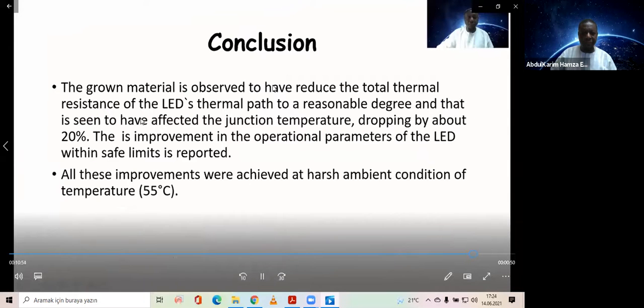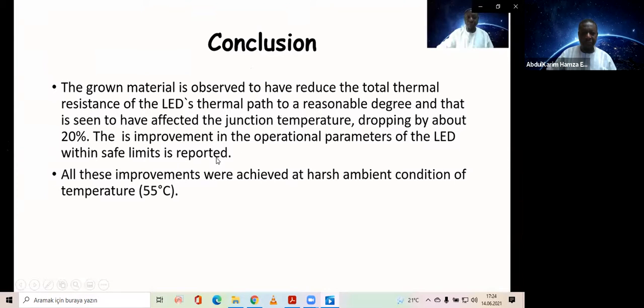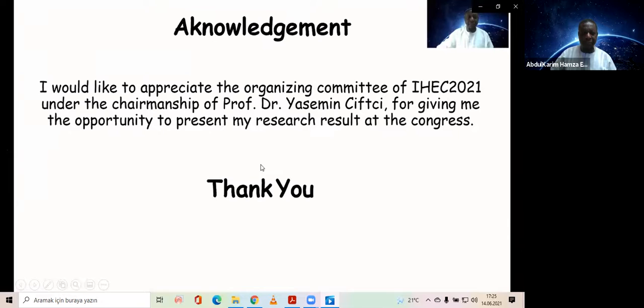In conclusion, the grown material is observed to have reduced the total thermal resistance of the LED's thermal path to a reasonable degree, and that is seen to have affected the junction temperature, dropping by about 20%. The improvement in the operational parameter of the LED within safe limit is also reported in the derating curve graph shown before this slide. And all these improvements were achieved at a harsh ambient condition of 55 degrees C.